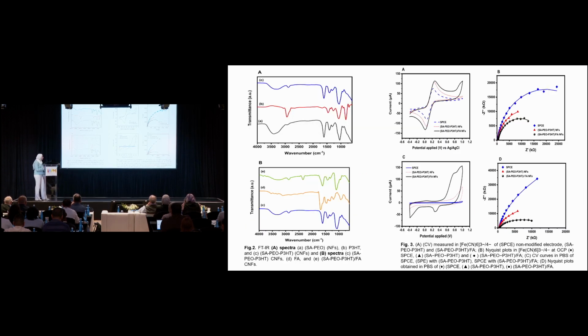Here we made characterization using the FTIR technique. We obtained the distinctive peaks for each polymer. For example, the broad band between 3,000 and 3,500 for the hydroxyl groups of sodium alginate, and the bands at 2,800 for the hexyl chains of P3HT. And after we added the folic acid, there is a decrease in all the bands. This may be related to the hydrogen bonds between folic acid and the hydroxyl groups and the hexyl chains.